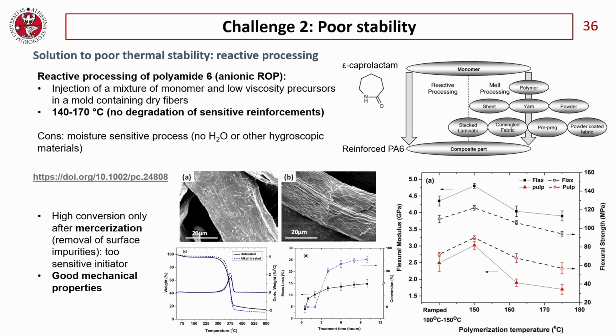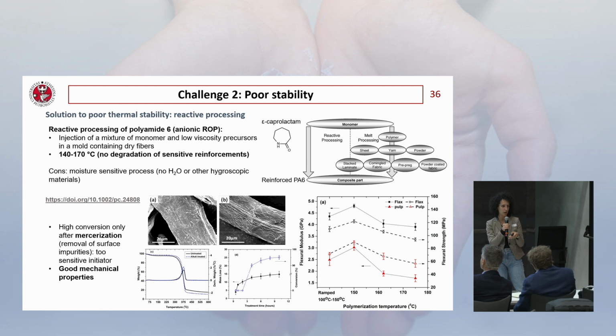These authors could achieve a high conversion only after mercerization of the fibers, because they use a too sensitive initiator, in my opinion, but they still achieve good mechanical properties with a PA6 flax composite. Very interesting. We actually work on this topic, on reactive PA6, in our lab.